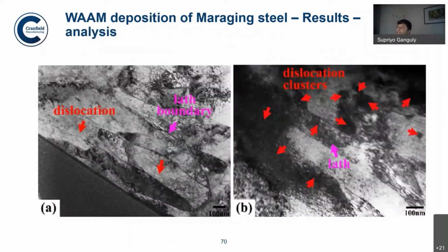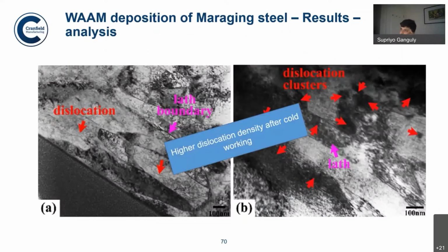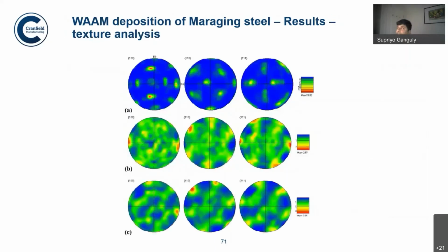So this is some further microscopy work that the student had done, just to show that the rolling generates dislocation clusters, which help with the next layer deposition. It then allows it to get a reformation. I would not say recrystallization, but I would say at least partial reformation of the grains, which are quite effective in achieving the solutionization which is required afterwards during the heat treatment.